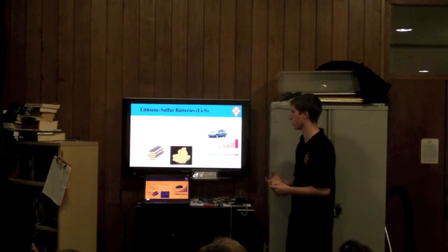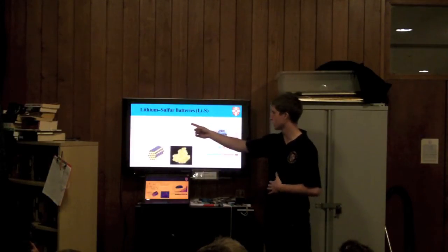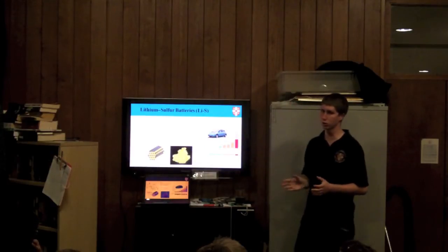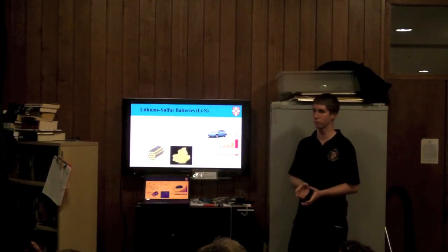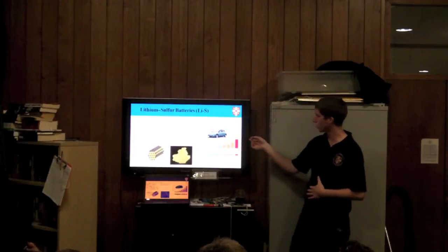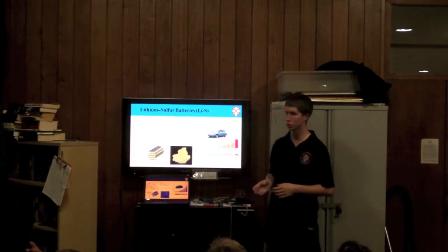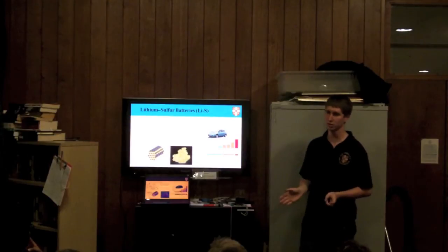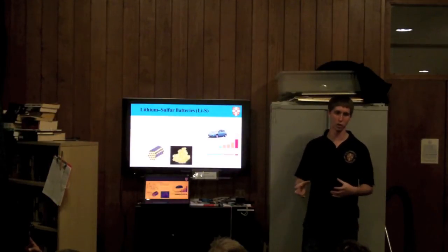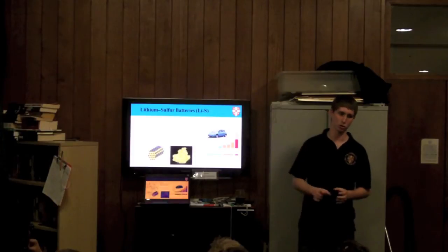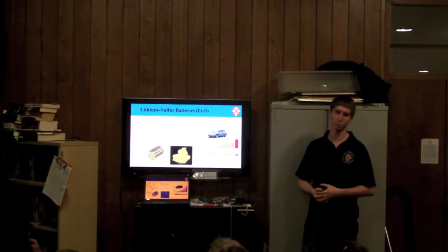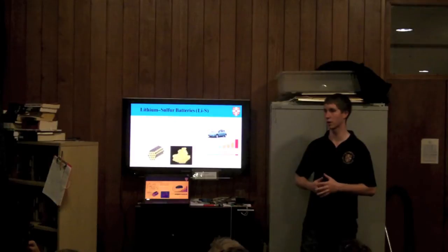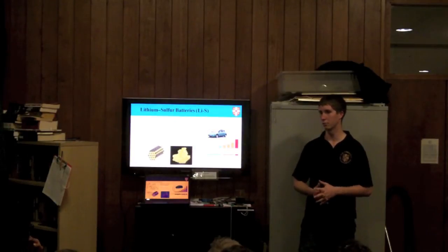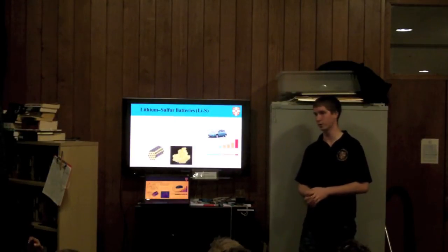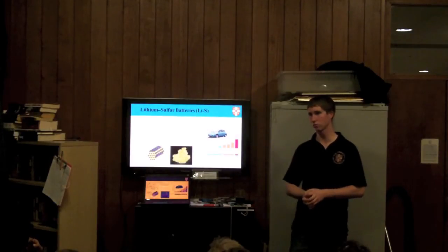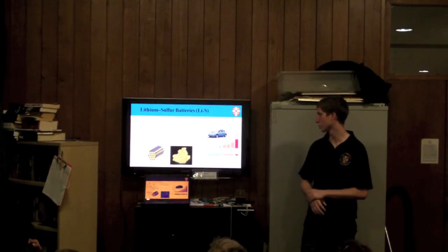So there are these sulfides that form on the way: you have just sulfur at one end, and lithium sulfide on the other end. But there are all these intermediates that have different compositions of lithium and sulfur. It turns out neither thing at either end of the charge and discharge is soluble, but everything in the middle is. And if things dissolve into your solvent, then you get short circuits because they form reactions throughout the separator, and this is quite complicated. So people are working on how we might find different solvents or different ways to set up the cell so that we don't have these problems with solubility.